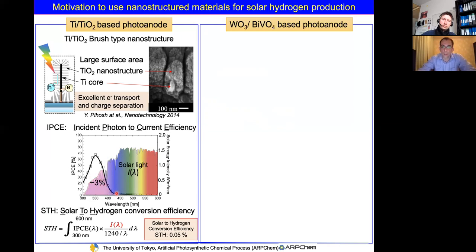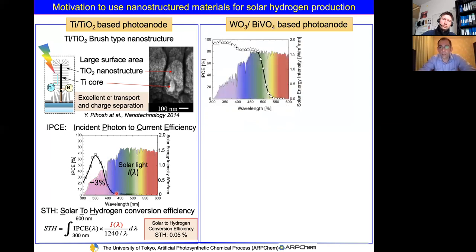However, if we now look at the bismuth vanadate material, the absorption edge is quite wide, around 550 nanometers, and we can utilize about 50% of the photons from the solar spectrum. The theoretical solar-to-hydrogen conversion efficiency that can be realized is 9.5%. As you can see, for titanium dioxide it's just about 0.05%, but here it is 9.5%. So it's a very excellent material.